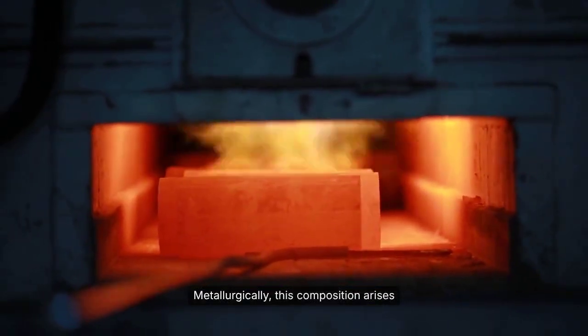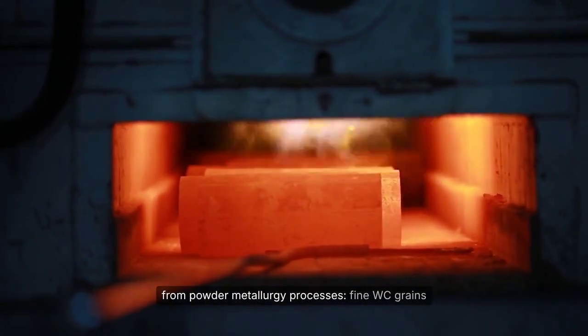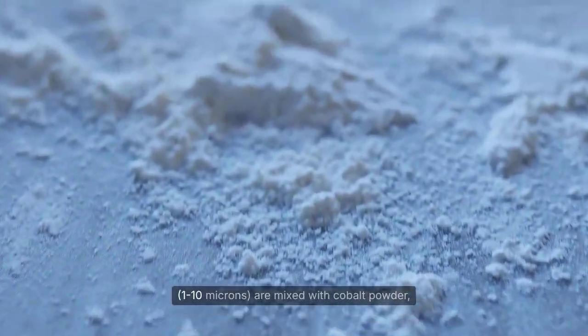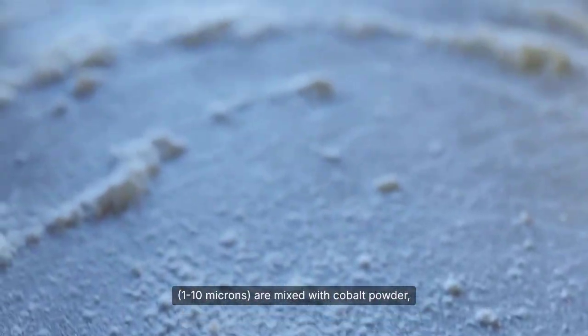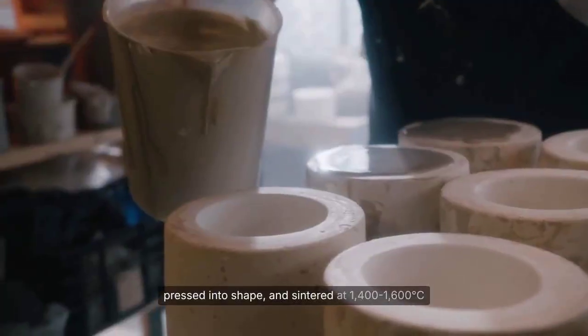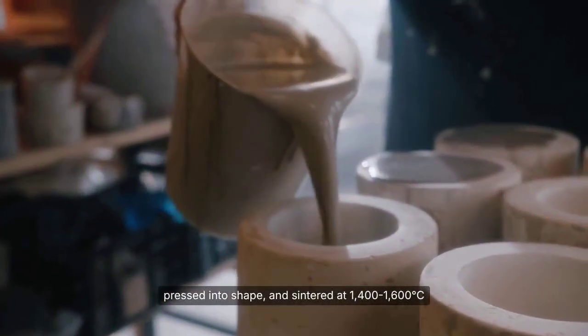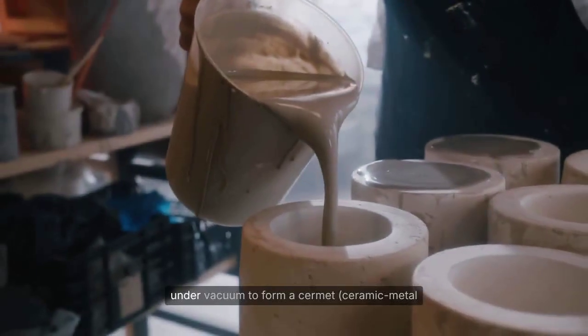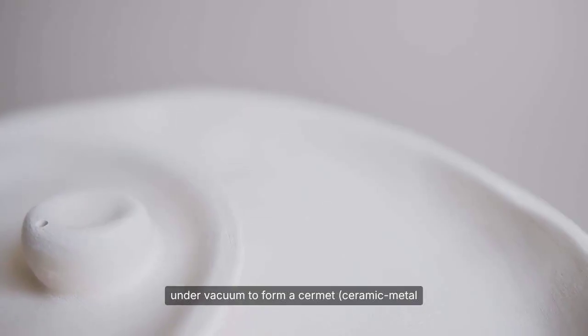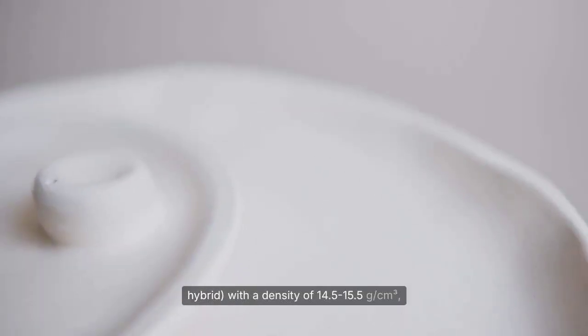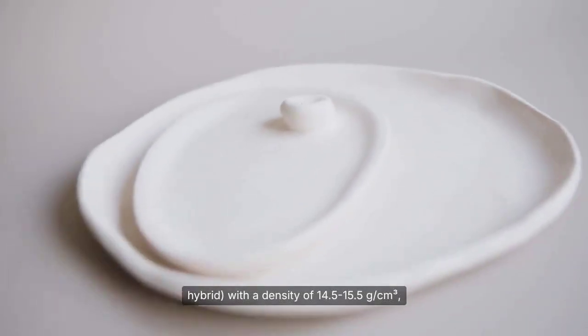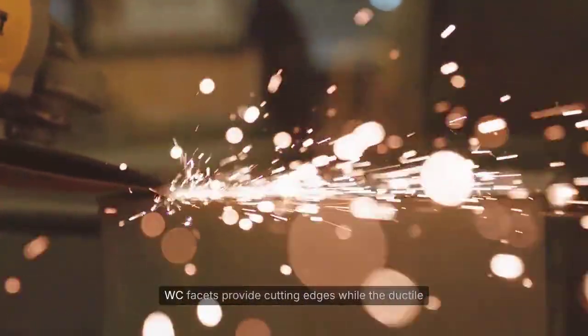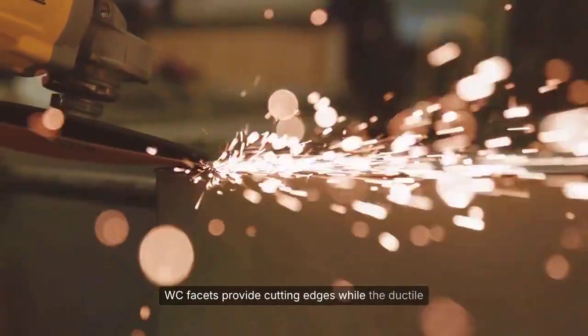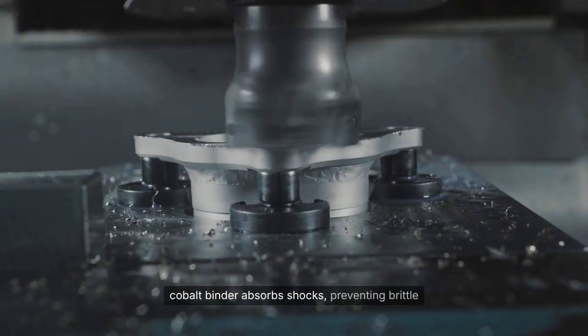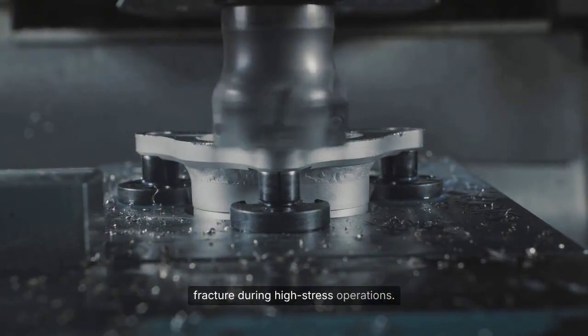Metallurgically, this composition arises from powder metallurgy processes. Fine WC grains, 1 to 10 microns, are mixed with cobalt powder, pressed into shape, and sintered at 1,400 to 1,600 degrees Celsius under vacuum to form a ceramic-metal hybrid, with a density of 14.5 to 15.5 grams per cubic centimeter, creating a microstructure where the angular WC facets provide cutting edges, while the ductile cobalt binder absorbs shocks, preventing brittle fracture during high-stress operations.